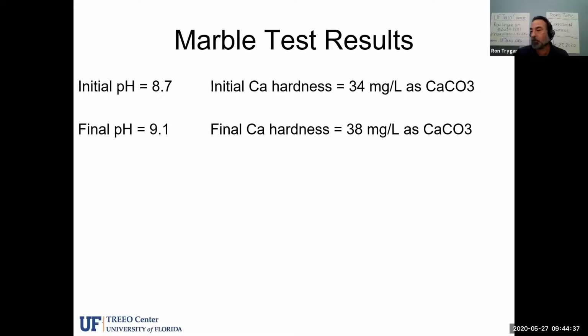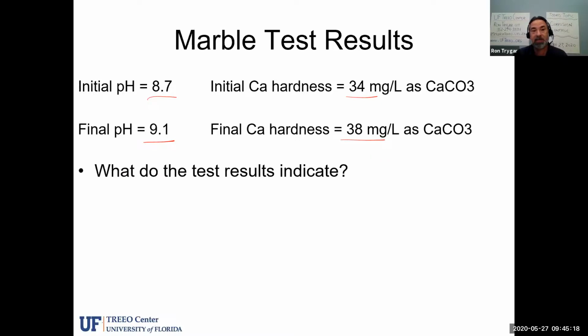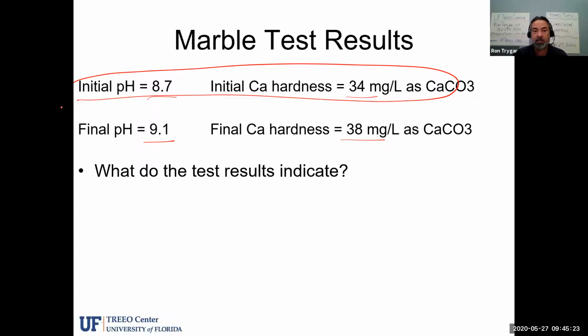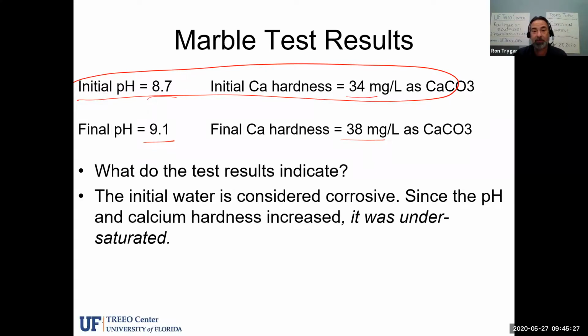So take a look at some marble test results we have here. We see an initial pH of 8.7, and the initial calcium hardness was 34 milligrams per liter. It sounds kind of low with a pH of 8.7, but the initial calcium hardness was around 34 milligrams per liter, so not a whole lot in there. When we added the calcium carbonate and dissolved it, let it settle out, and then filtered it, we come back and check the pH. Oh, pH went up to 9.1. Well, that's a pretty good increase. And the hardness actually increased up to 38 milligrams per liter. So what are the results telling us? The results are telling us that the initial water was, drum roll please, undersaturated and therefore considered corrosive. So it wanted the extra calcium and it was able to hold on to it. That is how those results would be interpreted.